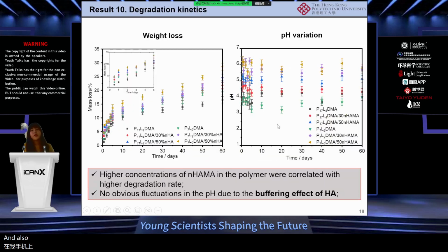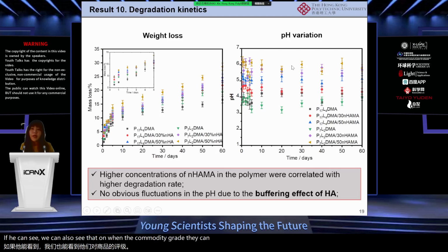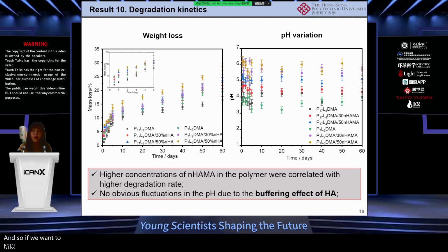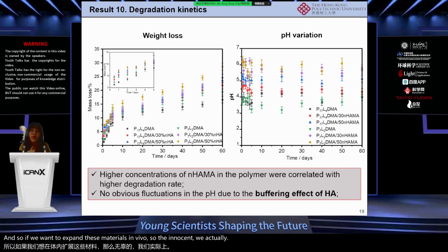And also we can examine the degradation of the composite materials. We can see that when the composite degrades, it can maintain the pH around pH 6. This is advantageous because it means that we have reduced inflammation. If we want to implant these materials in vivo, we want less inflammation.